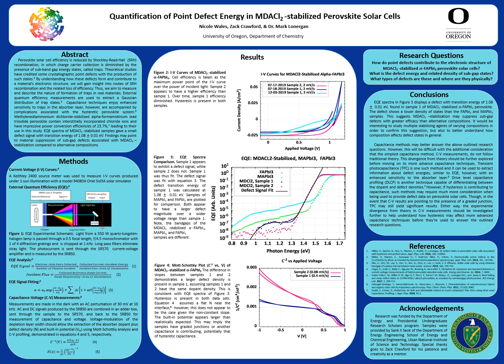Figure 1 demonstrates the procedure used in EQE, where light from the monochromator is directed to the sample, generating charge carriers. The subsequent photocurrent is then measured. The EQE signal is the number of carriers collected divided by the light incident, which is determined from a reference diode, as shown in equations 1 and 2. The EQE signal can be fit with equation 3, where the density of defect states can be extracted by fitting the second term of the equation.